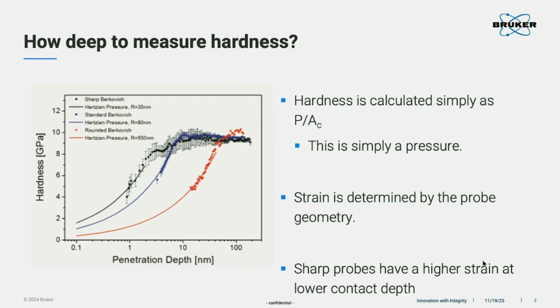So the stabilized zone is what we want, right? If we look at this, I think the smaller tips stabilize earlier. Earlier means shallow depths, so it's around 15 to 20 nanometers that it becomes stable. That's because the sharp tip can get the plastic deformation earlier.